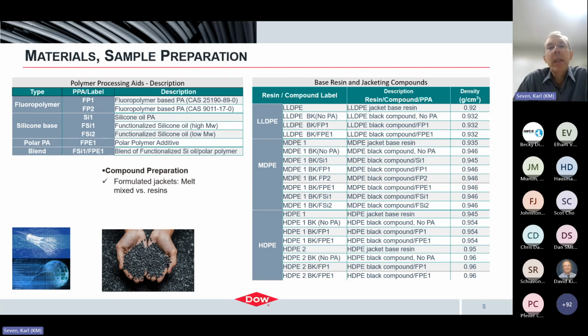But we also looked at and compared the performance of those to some non-PFA-based processing aids that were silicone-based, such as silicone oil, functionalized silicone oils, high and low molecular weights. Also looked at a polar polymer additive, as well as a blended system of a silicone oil with a polar polymer additive. These compounds were produced in a melt mixing process.